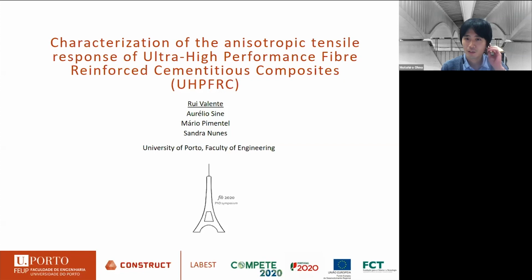Yes, important. You are right about that. This method is not advisable for those situations, for 3D characterization of the anisotropic behavior of UHPFRC. This method is only valid for thin elements because the magnetic field is more important very close to that ferrite magnetic probe.